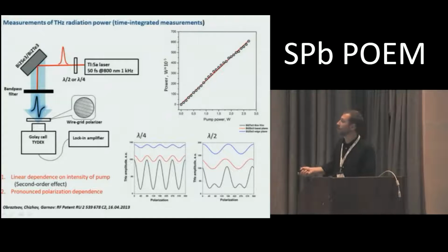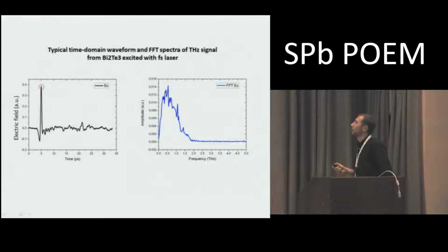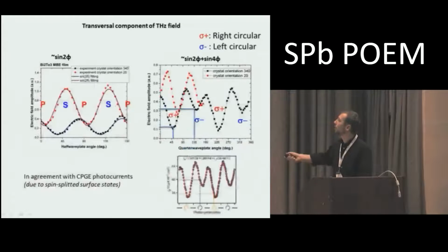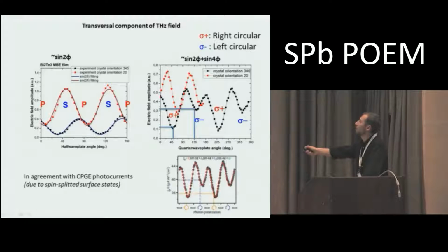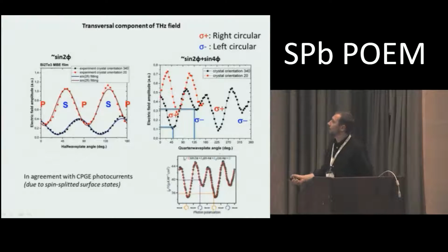And later on, we moved to time domain spectroscopy. So here are the typical time domain waveforms and terahertz spectrum obtained from this bismuth telluride sample. And by tracking the amplitude of the terahertz peak, we can observe these nice dependencies on polarization, and you can clearly see that the amplitude of the signal obtained under excitation with right circular polarization is different from the left circular. So these results are in agreement with photocurrent measurements, and can be interpreted as a circular photogalvanic effect. So we demonstrate that terahertz emission spectroscopy is a very powerful tool to get access to the electronic band structure of the material.